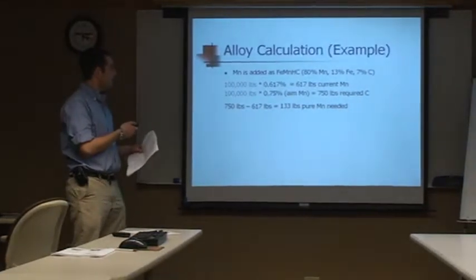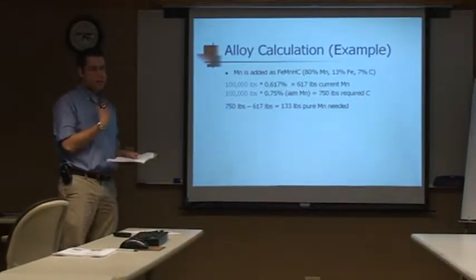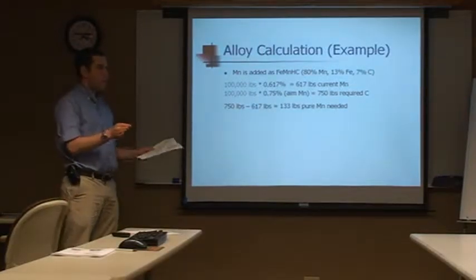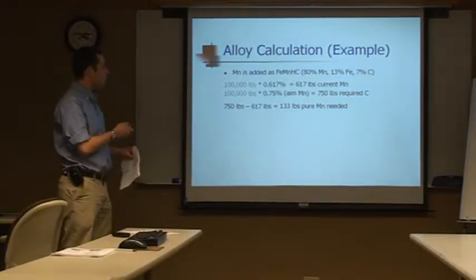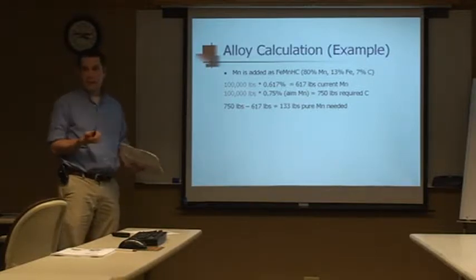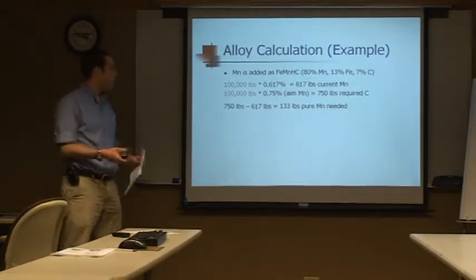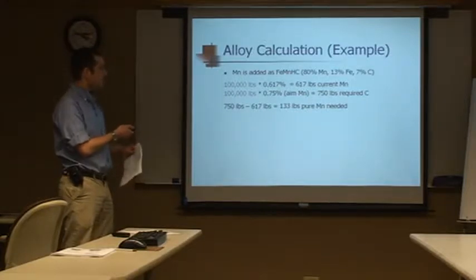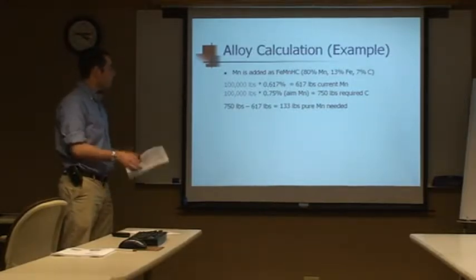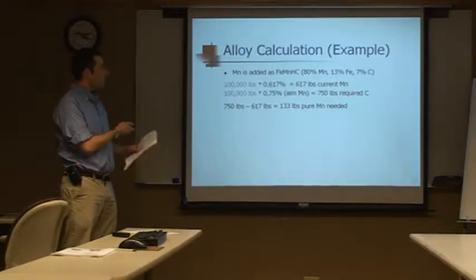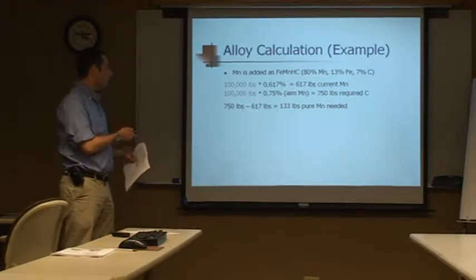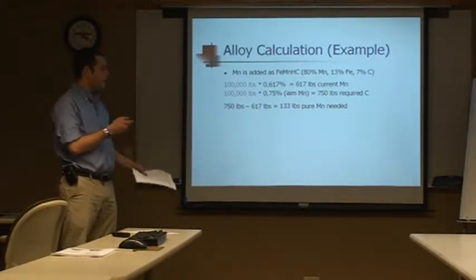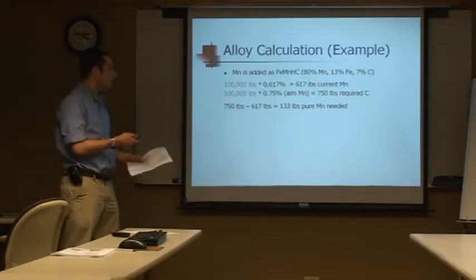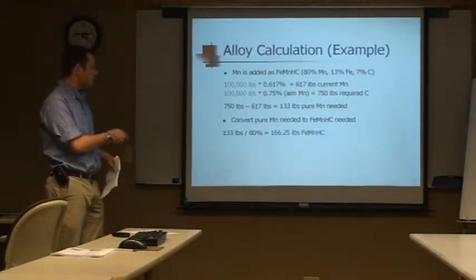All right, so back to the alloy calculation example. So we figured out how much carbon we need to put in eventually. Going to the manganese, manganese is added as ferromanganese, so it's not just pure chunks of manganese we're putting in there. It's a mixture of manganese, iron, and carbon. So we use the same process and figure out we have 617 pounds and we need 750 pounds. So that's 133 pounds we need of pure manganese. So we got to convert that now into ferromanganese.